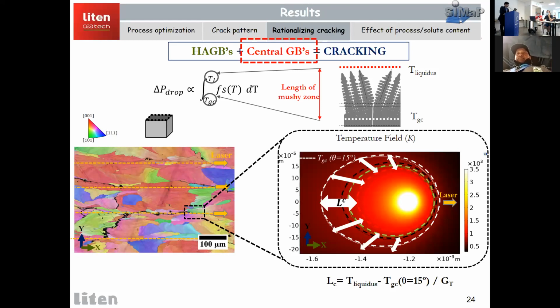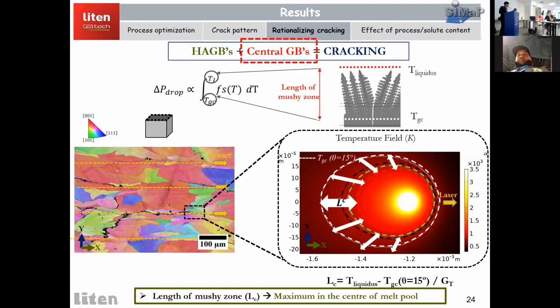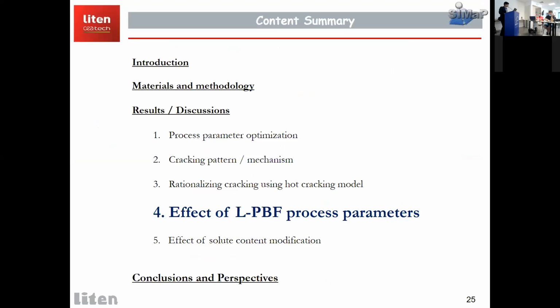So we clearly see that along the center line, we have a high length of mushy zone. And this suggests that we might have higher pressure drops in that particular region. And this explains why we have center line cracking in the topmost surface. Okay, now we have rationalized our cracking.